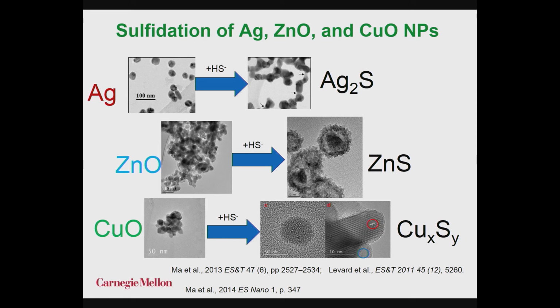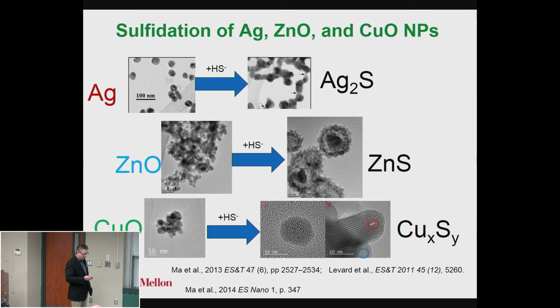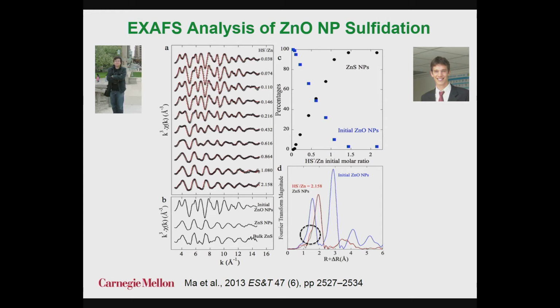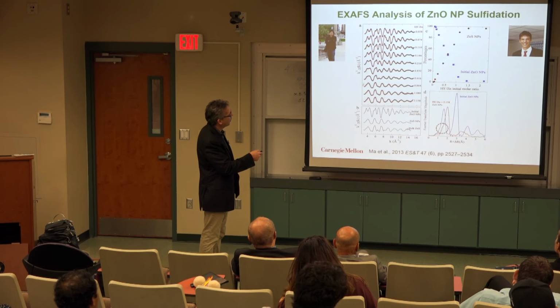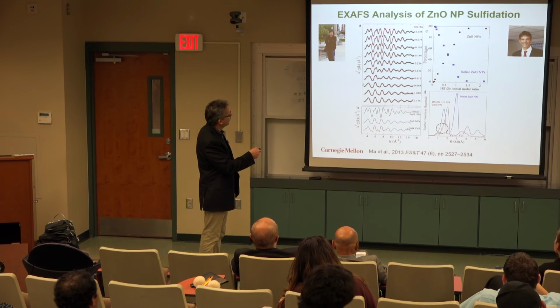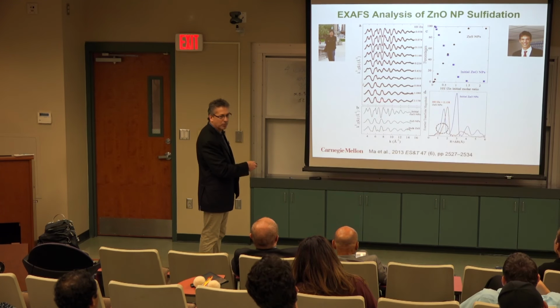And then, of course, we started sulfidizing everything. All these metals that we were working with, silver and zinc and copper, are all chalcophilic metals, so they love sulfur. So we would just expose them and sulfidize everything and get these different materials. And then, of course, we could use X-ray. What this shows you is the X-ray absorption spectroscopy for different sulfur to zinc ratios. So we took our zinc oxide nanoparticles, exposed them to different sulfur, and as we go higher and higher, clearly the zinc oxide spectrum is changing to something else.